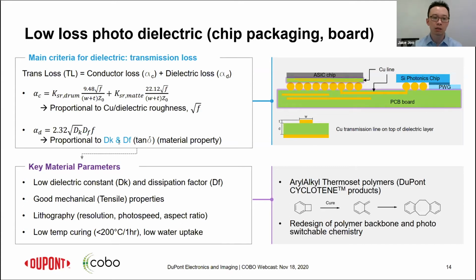As well as this electrical behavior, you also want to make sure that the mechanical stability is in place and matching the CTE properties. In certain cases, you also want a material that is photo-patternable if needed. And in certain conditions, you also want different temperature and curing and so forth. And of course, water uptake is also important, because water will eventually increase the Df as well.